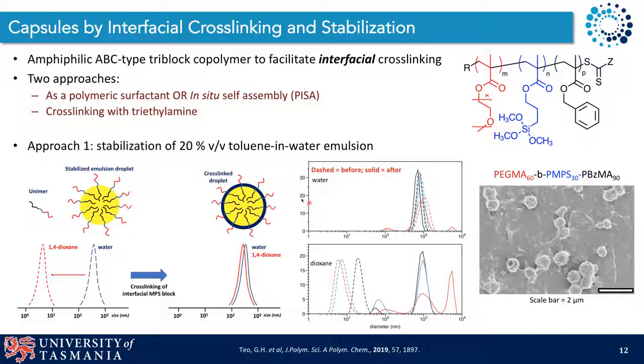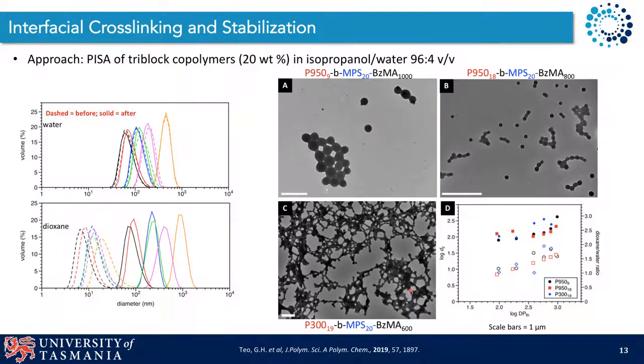What we were able to observe was that prior to the addition of the base, obviously we had the emulsion droplets, approximately a micron in size, form, with the solid lines post cross-linking and the dashed lines prior to cross-linking. If we add that system back to a good solvent, namely dioxane, we would see dissociation to the unimer state, but that was of course not what we observed in the case of post cross-linking, so we were able to preserve that capsule morphology in an organic solvent.